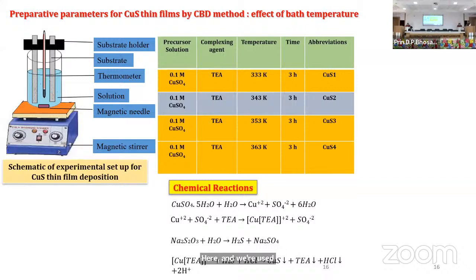Deposition is carried out at different temperatures. Time is same, which means that this experiment is done for changing the temperature and looking what is the effect of temperature on the morphology. That was the idea. So by keeping everything constant, 3 hours for the deposition, and using the very similar bath over here, and this is, of course, the reaction, how that film will be formed.